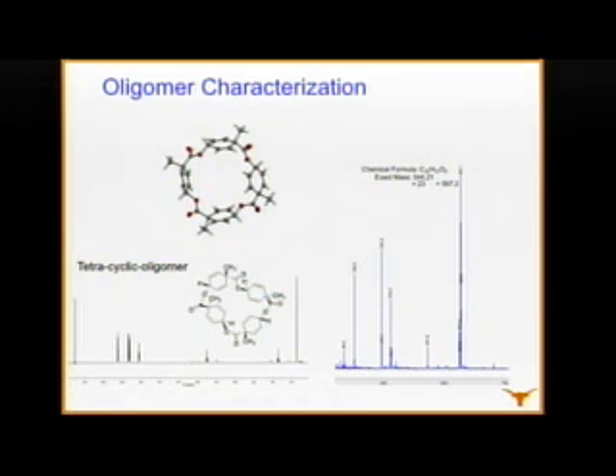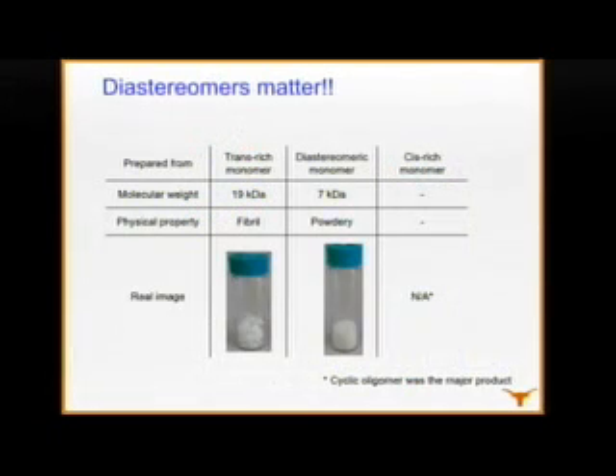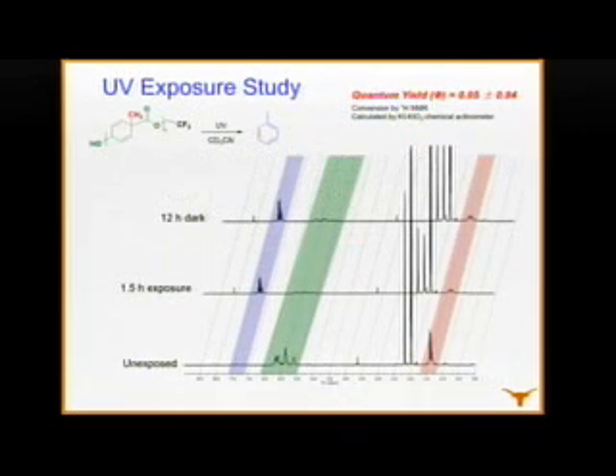Turns out that there are two diastereomers of this alcohol, hydroxy acid, and the one that has the alcohol and the carboxylic acid group cis on the ring forms the tetramer. The other one cannot. So we learned to separate them one from the other, and if you use largely this one, you get a nice polymer. This one gives a low molecular weight polymer, and the cis-rich fraction doesn't make a polymer at all. So here you see the example of shining light on the thing.